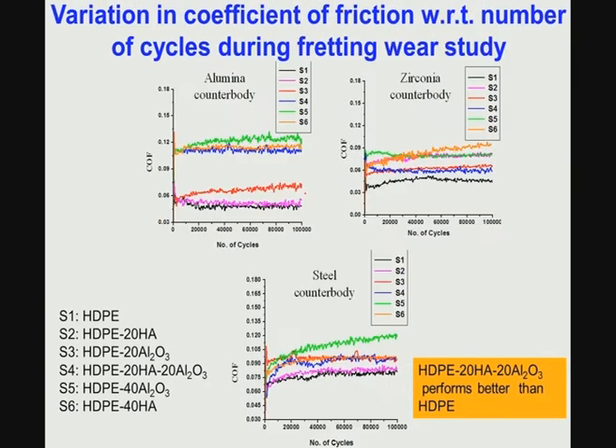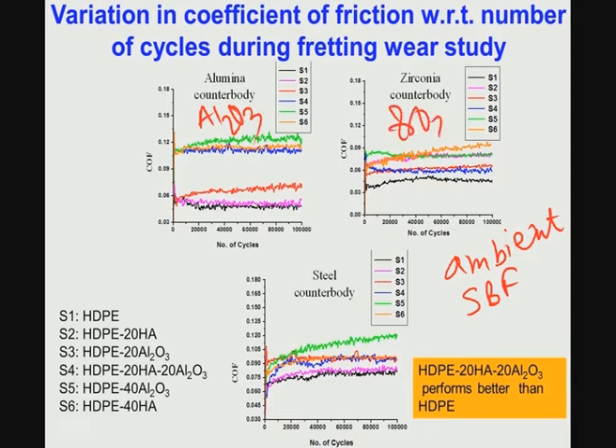Okay. And then you can measure the friction values, and these fretting experiments can be conducted under ambient conditions and under SBF conditions. SBF stands for simulated body fluid. So, under these two different conditions, whether you use alumina, zirconia or steel, in all these cases you see that the coefficient of friction typically varies in a close window of 0.07 to 0.12. Depending on the steel, zirconia and alumina, the steady state coefficient of friction is typically less than 0.1. So, the lower the coefficient of friction, the better it is.